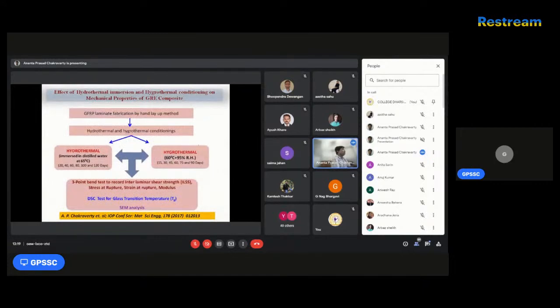Now let us come back to some of my works where I have used those characterization tools, found some properties and correlated them. First, I have fabricated this glass fiber reinforced polymer composite, where the polymer is epoxy thermosetting resin. After fabricating the materials, I exposed them to hygrothermal aging, where 95% relative humidity is there, and in hydrothermal, 65 degrees centigrade immersed in distilled water. All these are the parametric conditions for the environmental severities to which it is exposed.